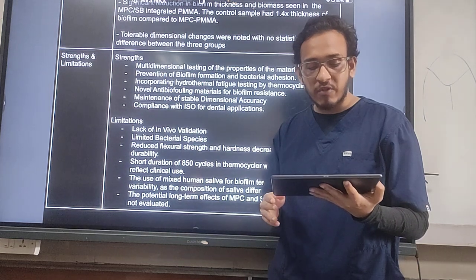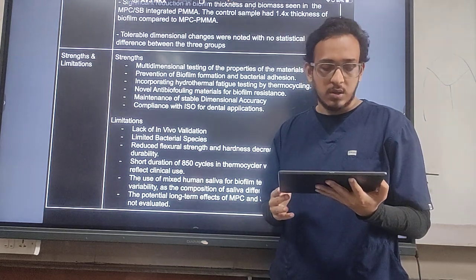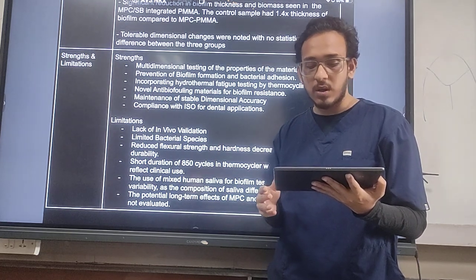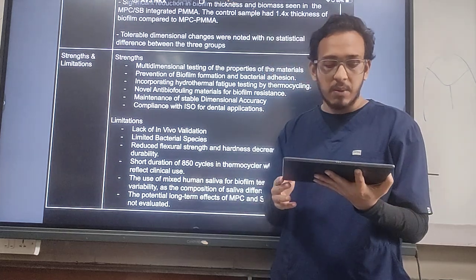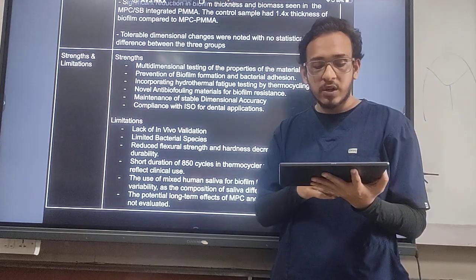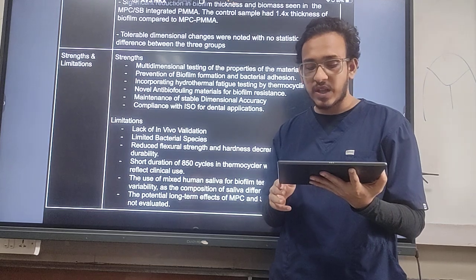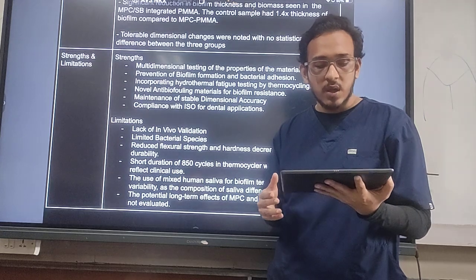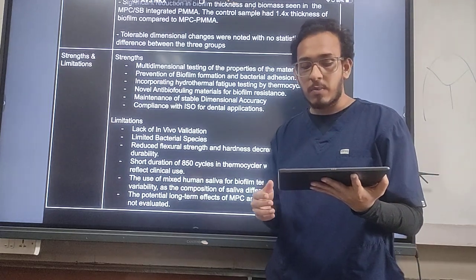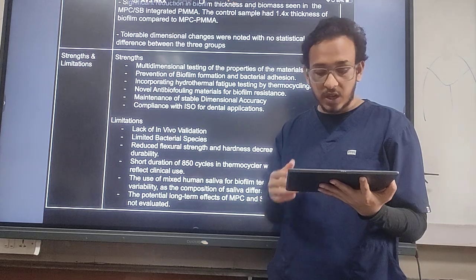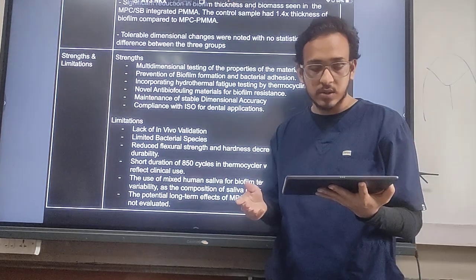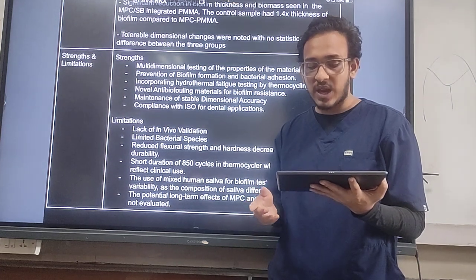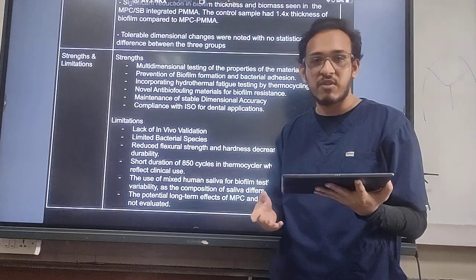Limitations: lack of in vivo validation, limited bacterial species, reduced flexural strength and hardness, decreasing long-term durability, and the short duration of 850 cycles in the thermocycler, which may not reflect the actual clinical scenario. The use of mixed human saliva for biofilm testing induces variability as the composition of saliva differs among individuals. Lastly, the potential long-term effects of MPC and SB on the oral tissues were not evaluated.